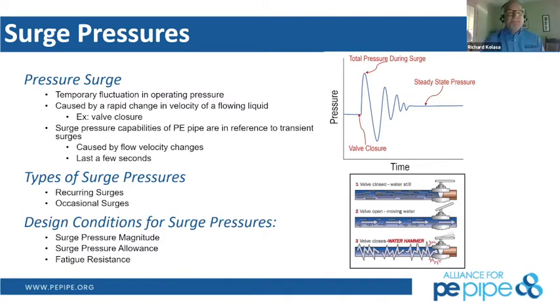Yes, Alan? In recent years, there's been more effort to understand transient surge pressures as well, on a very, very small scale, in the millisecond. Those pressures sometimes far exceed what we're talking about in 1.5 and 2 times, and the material property of high density polyethylene to absorb those really helps dispel any type of transient pressure. Those typically are seen right at where that change in velocity is occurring. A lot of times municipalities have gone to high density polyethylene outside of large pumps or other things of that nature in order to try to absorb some of those pressure transients as we go through it.